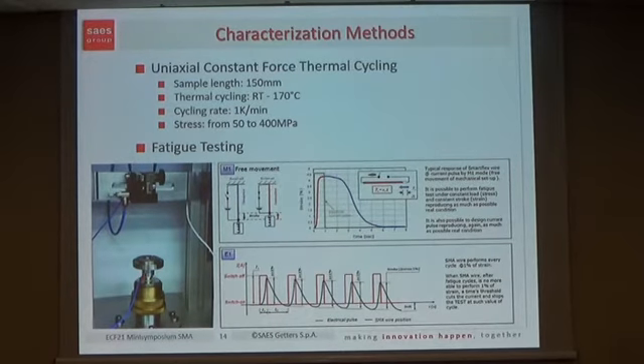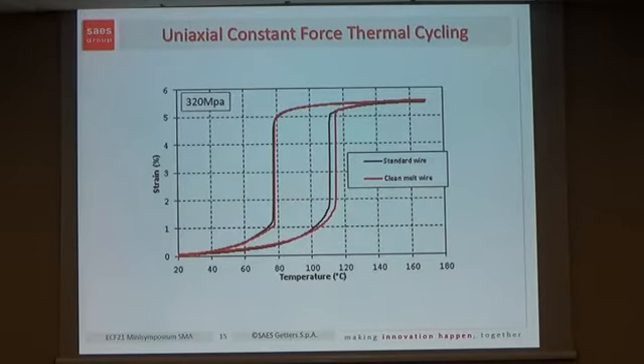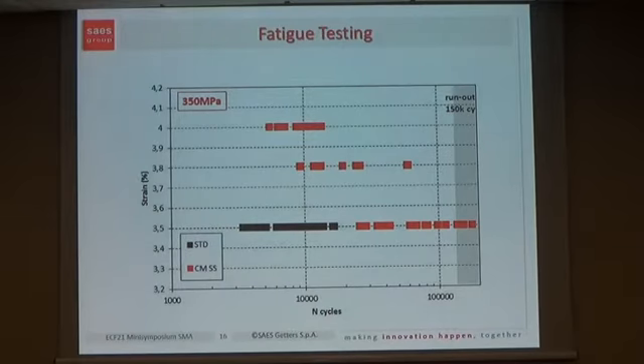We characterized the wire to be sure that everything was perfectly in line, and I won't enter into details about the characterization method. We typically use uniaxial constant force thermal cycling and the fatigue testing according to the sketch reported here. I would say the hysteresis curves are similar, so nothing special or any significant differences. And these are the fatigue tests. We select here 350 megapascal, which is quite a stressed condition for a 25 micron wire. You see in red the wires produced by the improved alloys, and in black the standard.